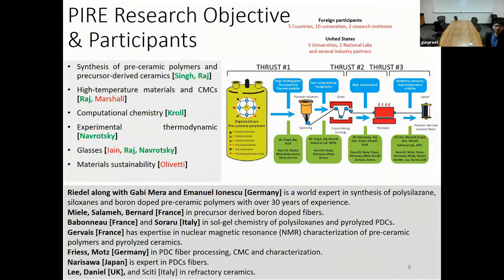The goal of our research objective of our PIRE project is to basically move away from these expensive binary silicon carbide systems to multi-component PDCs. When I say multi-component, I'm talking about silicon, carbon, nitrogen, oxygen-based systems. These multi-component ternary and quaternary systems are derived from organosilicon polymers that are low cost, and some of these actually can be handled in open air, and that reduces the processing cost. In addition, for these multi-component PDCs, SiCN for example, or SiOC, the processing temperature is about 1000 degrees C, which is half that of silicon carbide, and that reduces the cost as well.